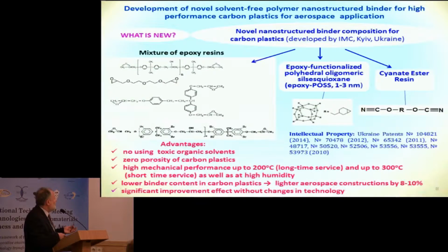It's the necessity of using solvents, which are toxic and lead to environmental pollution, and low thermal stability, low strength and low adhesion to carbon fiber at temperatures higher than 80 degrees centigrade, and also high porosity of carbon plastics, more than 20%. And it cannot give us the safety of the final product. Aircrafts, for example.